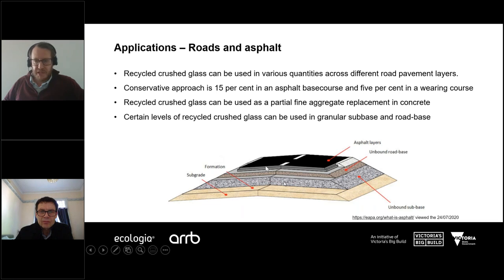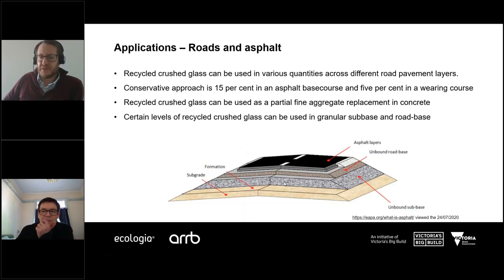So there's options to use it in asphalt layers. Typically in an asphalt base course, we could be considering up to 15% by mass of asphalt, or a more conservative approach around 5% in an asphalt wearing course. And I'll come on in a bit more detail as to why that's the case a bit later. There's also the option to use recycled crushed glass as a partial fine aggregate replacement in concrete. And also certain levels of recycled crushed glass can be used in both granular sub-base and also granular road base.